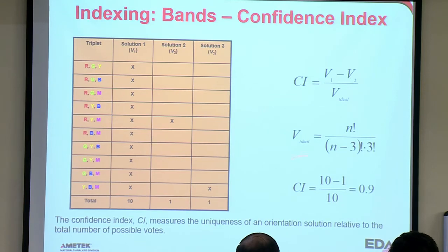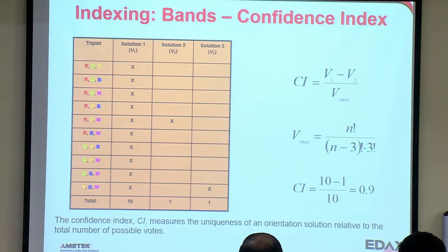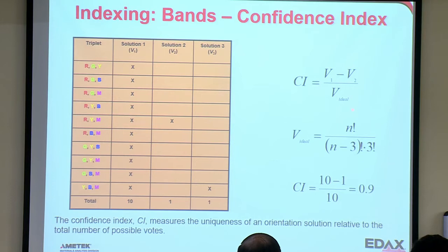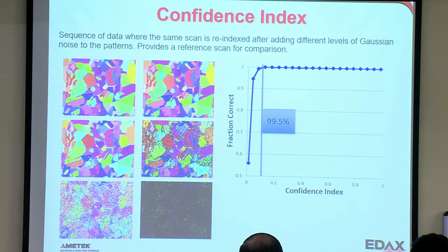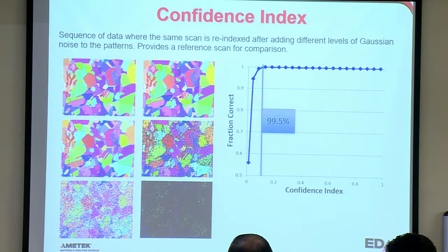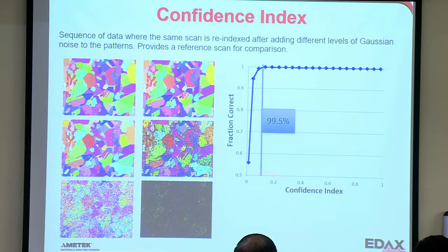Now if you think about this, let's say we have 2 solutions that are really close to each other, and it has a hard time finding the right answer. Then we would have a confidence index of 0. It doesn't mean we got it wrong. It just means we have a 50% chance that we got it wrong. And so a confidence index of 0 doesn't necessarily mean that it's wrong. In fact, I went in and did a study where I took a scan like this, added noise to the patterns, and then tracked the indexing with increasing noise. And what we ended up with is a curve that looks something like this.